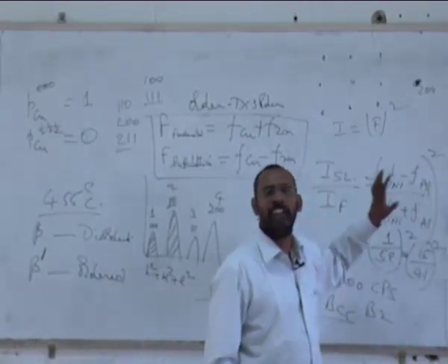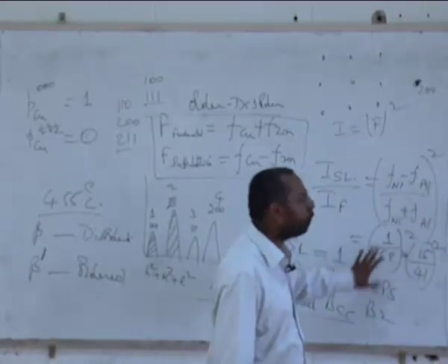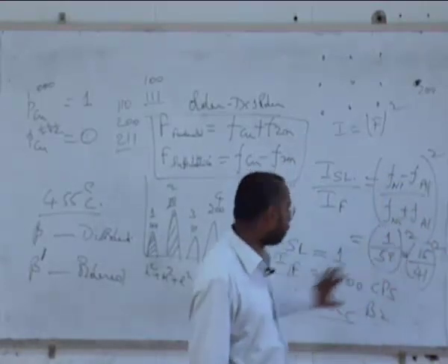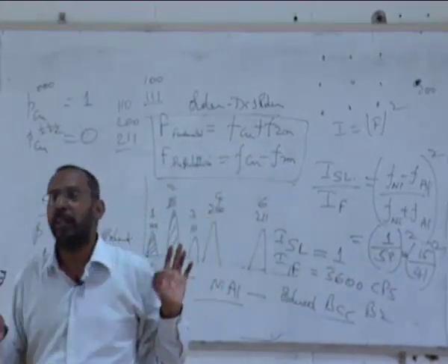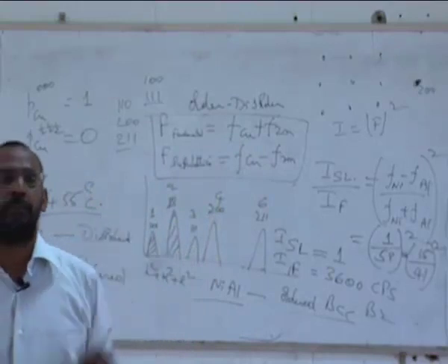So X-ray diffraction has that limitation: you will not be able to see copper zinc as an ordered structure, but you can see NiAl as an ordered structure, whereas with TEM you are not bothered about that limitation at all. You can see both of them.